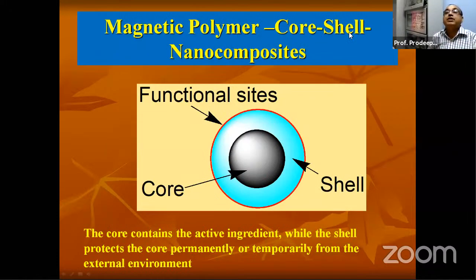Then here, magnetic polymer core-shell nanocomposites. First you take this core, this is a magnetic core, that means it is a magnetic nanoparticle, and this is a shell. Then finally you get functional sites. That means you take the core, then do polymerization, because in such a case, this polymer coating on the surface of the magnetic nanoparticle protects the nanoparticle from agglomeration, and then on the surface you hook some catalytically active metals. So you see here, the core contains the active ingredient, while the shell protects the core permanently or temporarily from the external environment.